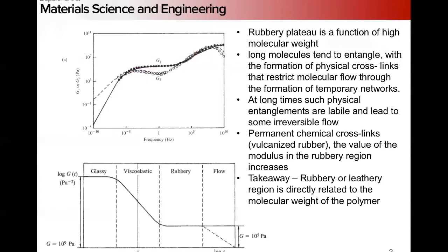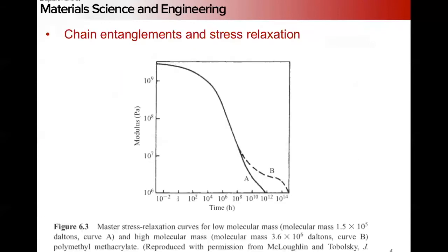But if we have long times, we're considering a load that's active for a long time, especially at an elevated temperature, right, these physical entanglements become labile and lead to irreversible flow, right? They're not permanent. They're these kind of slip links or chain rearrangements that can then allow further flow. If we have permanent chemical crosslinks, like in vulcanized rubber, right, our quintessential elastic material, the modulus of this rubbery region tends to increase, right? So this rubbery or leathery region is directly related to the equivalent molecular weight, right? How entangled things actually are.